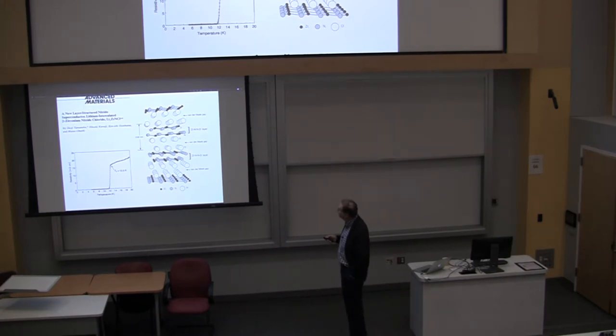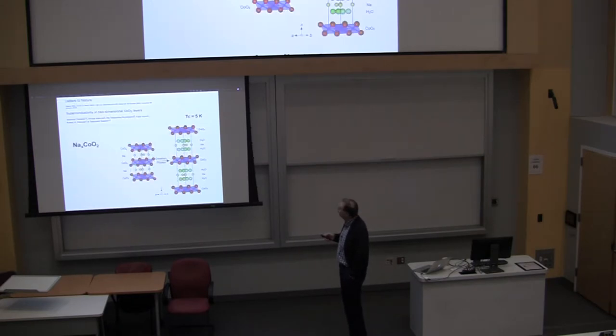So here's another example. You've got this lithium-x zirconium nitride chloride. And when you lithium intercalate this one, it becomes superconducting. And we'll come back to this one in a little while with non-conductive gating, as you see. And this one is also quite interesting. This is the sodium-x cobalt O2 system. So this has cobalt O2 layers separated by sodiums. And if you put water in between the layers, you can produce a superconductor. So that was kind of interesting. Takeshi calls it a watery superconductor. So we did quite a bit of work on that.